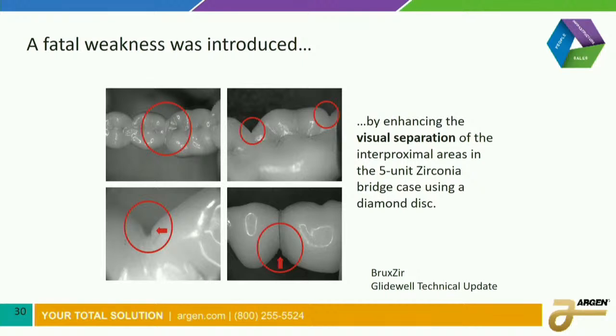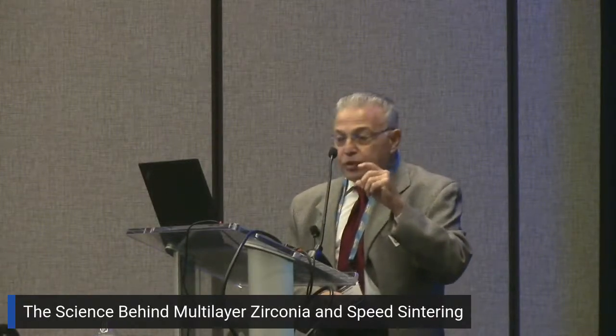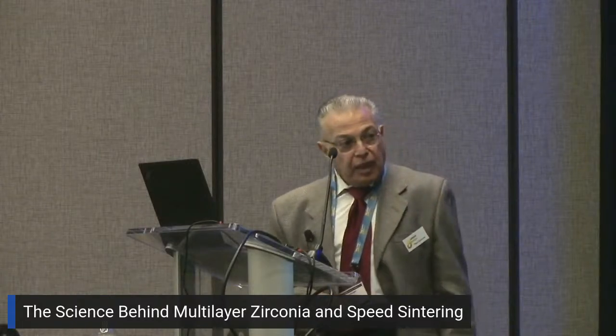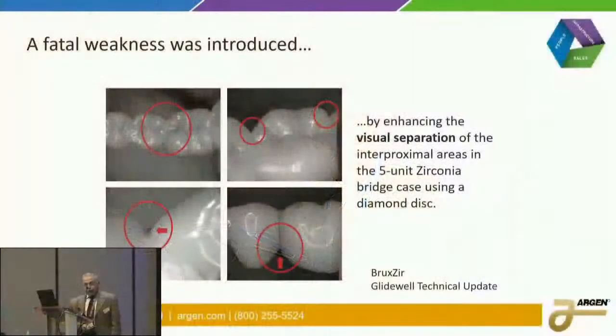prior to sintering, because when you apply a diamond disc onto sintered zirconia, you're adding energy into the zirconia, and anytime you add energy into the zirconia, it wants to transform, and when it transforms, it increases in size by 7%. Now, a good visual on that, just consider what happens when you put an ice cube tray in your refrigerator. When you take it out, those ice cubes are larger than the water volume that you had put in. And that's exactly what happens with the zirconia when it transforms. As a matter of fact, it increases a little more than the water does in the ice cube tray. So that difference in size causes the zirconia to fracture. And unfortunately, zirconia does not heal itself. The fracture happens at the speed of sound, so you're not going to stop it.